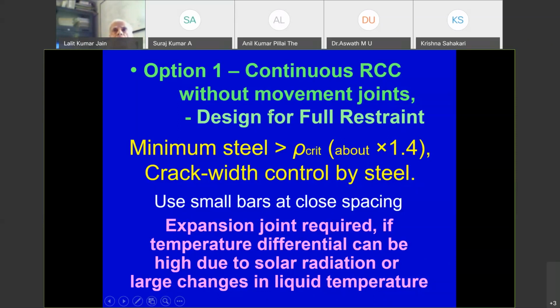You cannot have the option that you don't have joints or that you are providing only critical steel. You have to be at least 40% higher than critical steel, and this can go to double or more than double also. That depends upon your structure and the grade of the concrete and the shrinkage character. We have to limit crack width, and to limit crack width we require steel. Critical steel we can provide as a smaller percentage. You have to increase the steel to check the crack width.